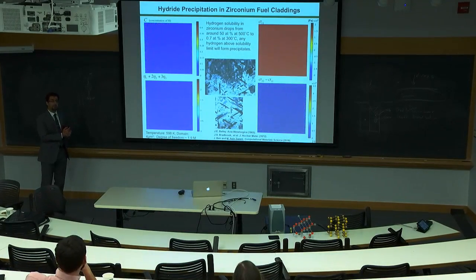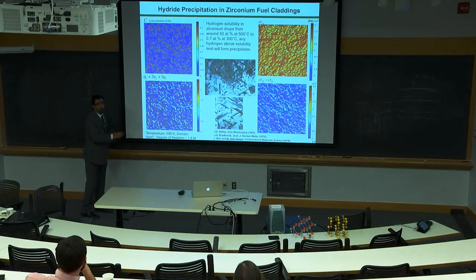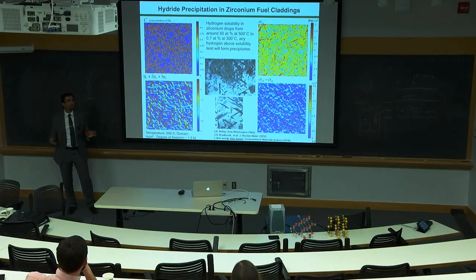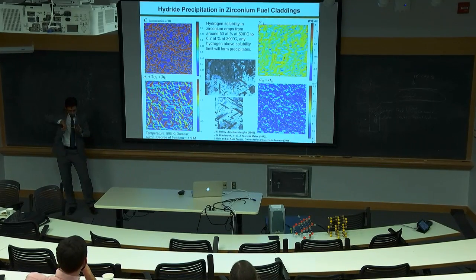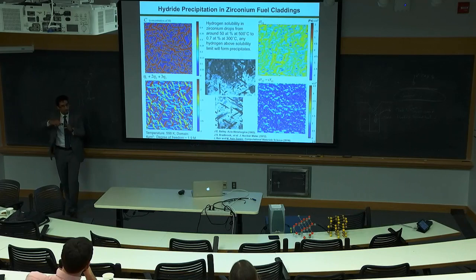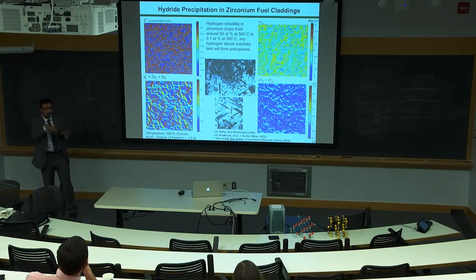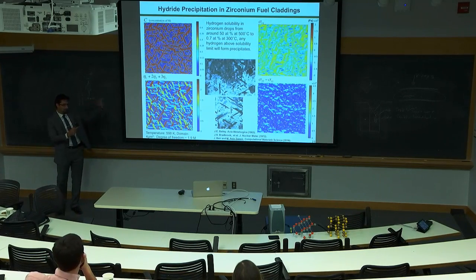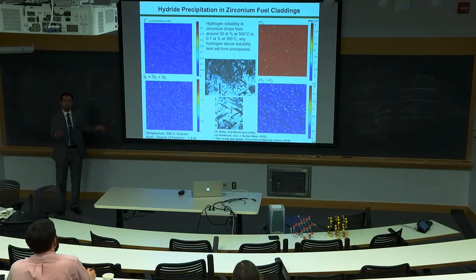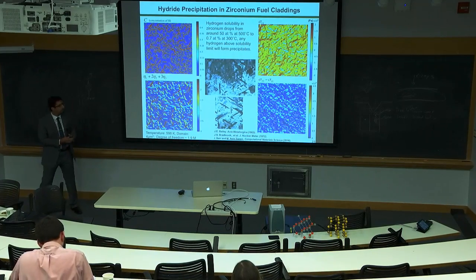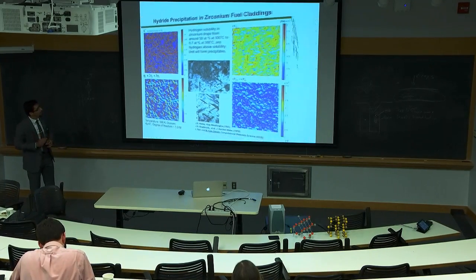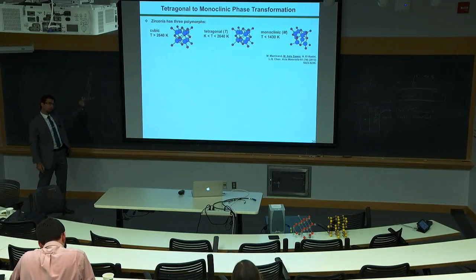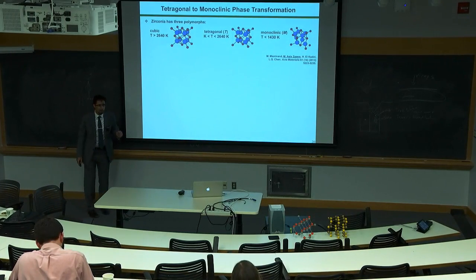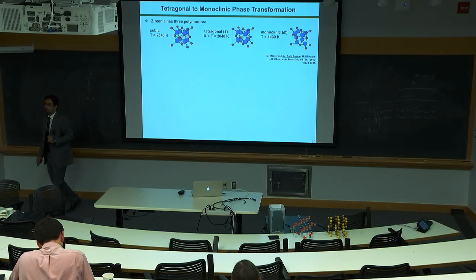Generated stresses. These are at the gigapascal level. So if you have precipitates that are brittle phases, you have very high stress fields around these precipitates. It's basically promoting cracks to propagate faster and faster. Catastrophic failure could happen. But again, I mentioned that I'm not going to go into the details of oxidation and hydride precipitation. Let's go back to the phase transformation.